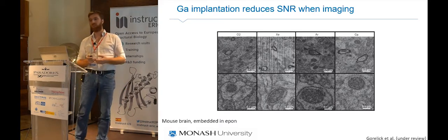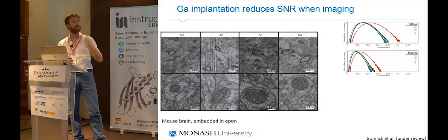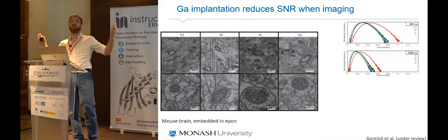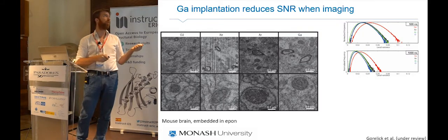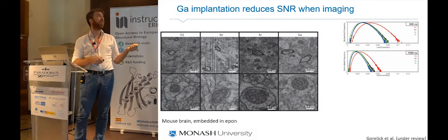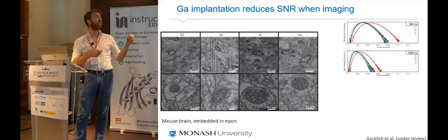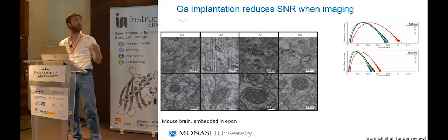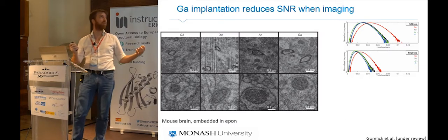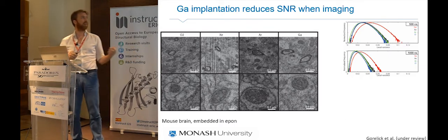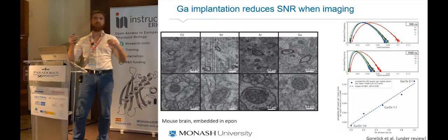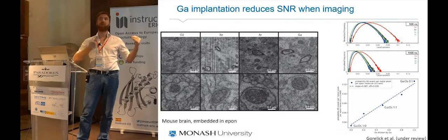And we tried to quantify this. We figured out that by taking measurements of the local variance, which tells you how much noise you have locally, the distribution of the local variance in images that were acquired after milling with a liquid metal ion source showed there was more noise essentially. And the reason is because of the implantation, as this phenomenon was explained at the beginning.